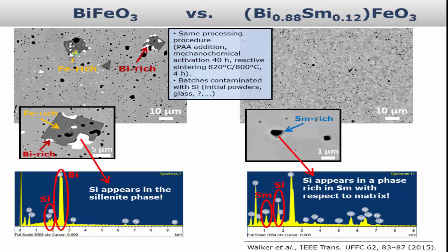When you start to modify the bismuth ferrite chemically, for example, with samarium, the concentration should be high enough. You basically go into a ternary system, and that changes the phase relations. So if you have silica, you now have a quaternary system: bismuth, iron, samarium, silicon. Could be very complex, but still different than in the case of bismuth ferrite.